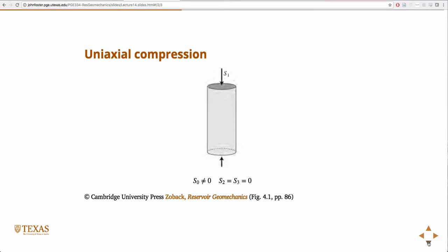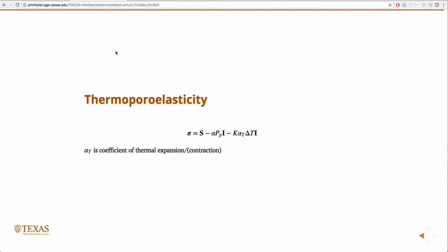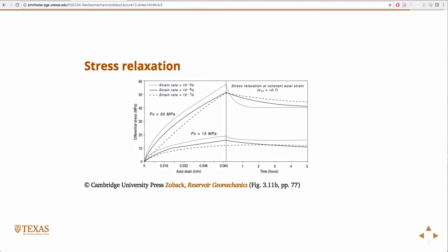And it's useless because of this. Rocks, look at the difference in a 35 MPa increase in pressure, and how much different the rock responds. In geomechanics, and even in civil engineering or something else, the rocks are always under confinement. There's always some hydrostatic confinement. So you always have to consider the external pressure on the rock, and it vastly alters the response of the material.